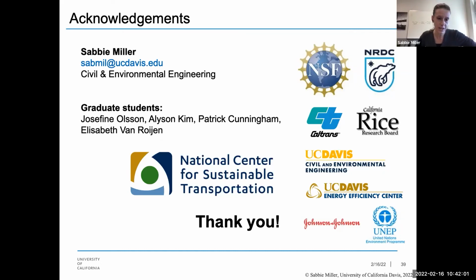So I do think it could lead to some significant benefits, depending on, of course, the individual ability of groups to actually make that shift. For example, if we are prescribing a specific amount of cement or cementitious materials for a concrete mixture on a per volume basis, then we could potentially be over-prescribing the amount of cementitious materials actually needed based on what the material needs to do. So if we're saying that for any cubic meter of concrete, we need to have 400 kilograms of cement in that, oh, sorry, I realized I do everything in SI units, so I do apologize to folks that use US customary. But if we're specifying a high level of cement, or even just a level of cement for a volume